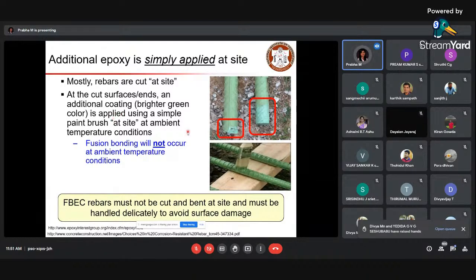So the rebar should not be cut or bent at the site. Even if it is cut or bent, you just pour additional coating to fix it, but this is not going to serve the purpose, and it will worsen the condition. As the thickness increases, the coating efficiency becomes less, and that may deteriorate and lead to other damages.